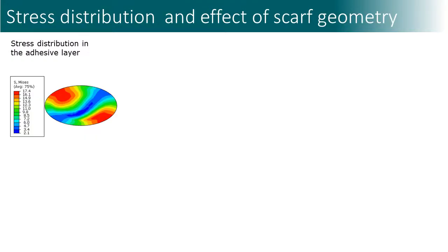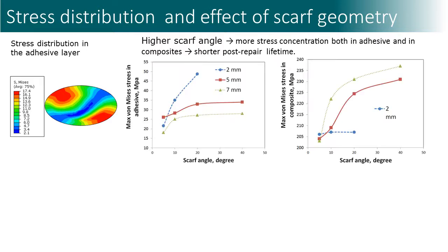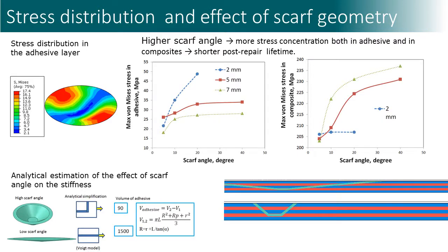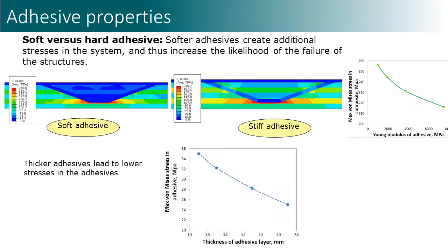Here, you can see the stress distribution in the adhesive layer between the scarf and damaged laminate. The higher the scarf angle, the higher the stress concentration in the laminate, and the shorter the post-repair lifetime. Also, softer adhesives create additional stresses in the laminate.